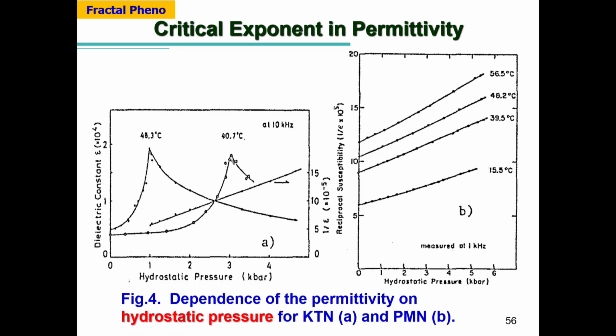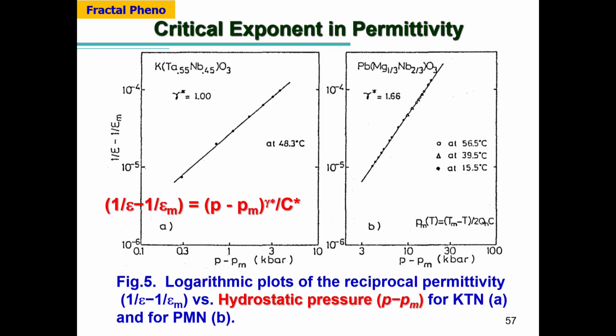Of course, temperature itself is not quite sure, so we worked on the hydrostatic pressure dependence. Similar to the temperature dependence, we observed some irregular, concave shape here. Therefore, we again fit to the log-log scale to determine gamma. So potassium tantalate niobate, this is beautifully 1. And the PMN is around 1.7, okay?